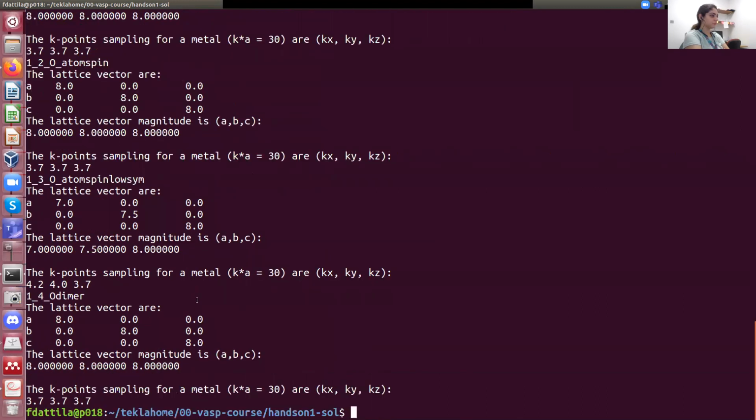And the other thing that you could have done was also to move what? In this case, you just have a single oxygen, so it would not have worked. But if you have two atoms, you can also move slightly one of them, again, to break the symmetry. And that would be the same, for instance, if you have a CO molecule. If you put the CO molecule on the surface, adsorbed like that, then again the system is very symmetric, so maybe you will not get to the lowest energy configuration.